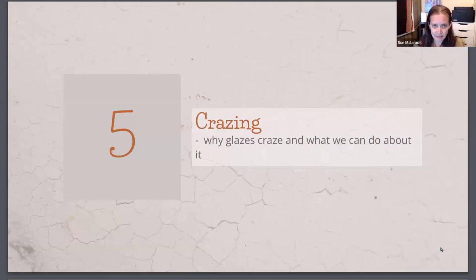It's called glaze fit, and it's related to thermal expansion. As our clay and glazes are heated and then cooled, everything expands and contracts. And if they don't do that at the same rate, then we have glaze fit issues, which can lead to crazing. If you don't know what crazing is, I'll have examples, but it's where your glaze crackles and you hear those pings when you open the kiln.